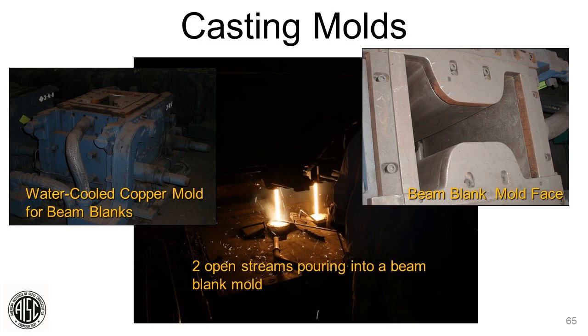All right, so on the left-hand side, you see a water-cooled copper mold. On the top right-hand side, you can see the semi-finished dog bone shape in the copper mold right there. And in the middle section, you'll see we're actually pouring 2 streams of steel right into the mold web, into the web flange intersection right there. We use that to make sure we have a uniform flow. If you stuck it right in the middle, we wouldn't have sufficient flow to the toes of the beam blank. So we use 2 streams.